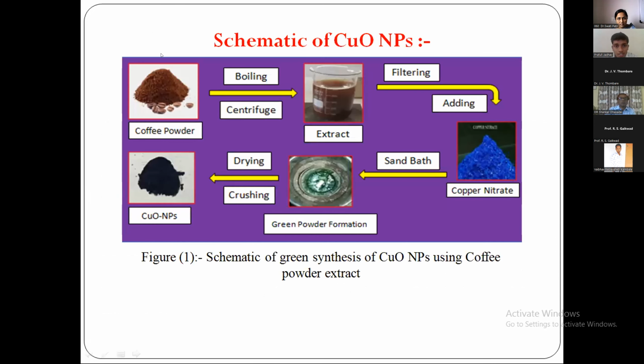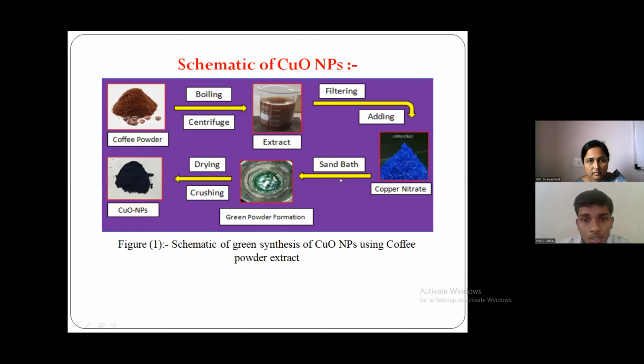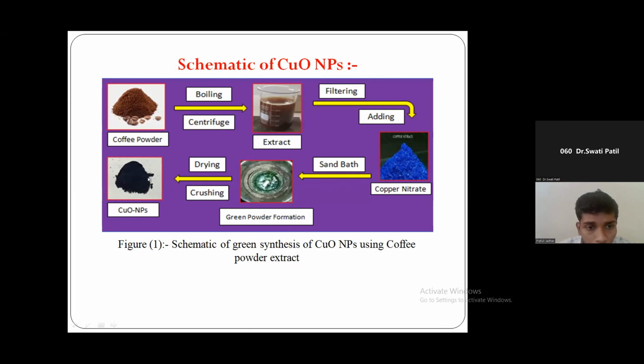Before that, this is a schematic which shows the formation of copper oxide nanoparticles. This is a coffee powder. Here it is an extract. This is copper nitrate. Simply this was added to the extract, and the container was moved to a sand bath. Then continuous stirring was done for about 12 hours. This green color powder was obtained, and then after the calcination process, these nanoparticles were formed.